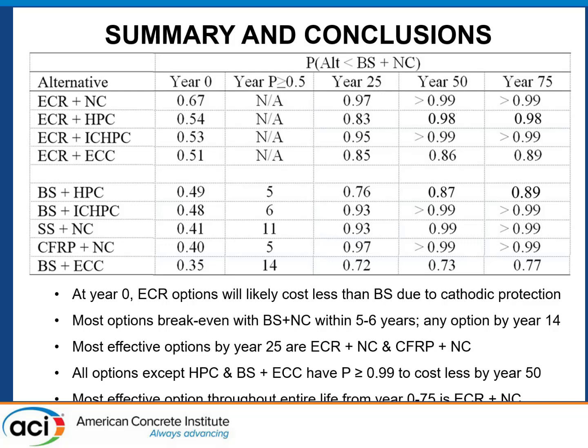In other words, even the very most expensive one, that black steel or unprotected steel and the engineered cementitious composite link slab, it's only a 35% chance to cost less than the normal steel and the normal concrete option. The second column there, the year that probability is at least 0.5, that's essentially the break-even year. In other words, when do we expect each of these options to have an equal likelihood to cost less or more than the baseline? And as you can see, almost all of them there expect to break even by about 6 years from the initial construction. And only a couple options there, the ECC link slab and the stainless steel bars, take a little bit longer to break even at 11 and 14 years, respectively.